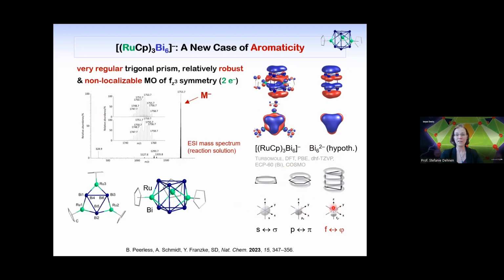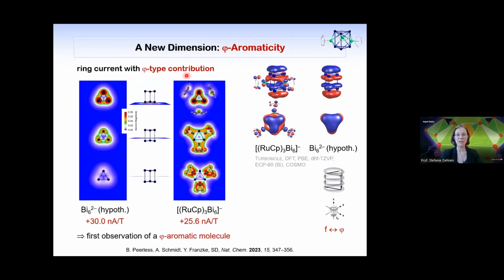And what we find here is something that we would refer to as an F atomic orbital. So it should be phi type in symmetry. And as we found out that this is actually non-localizable, so we have this phi type orbital without localizability, we have also ring currents that we can calculate with reasonable numbers. And this is why we introduced this molecule as being the first one to be observed as a phi aromatic molecule.